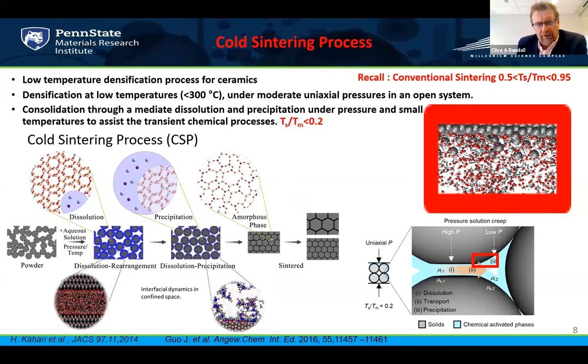So we've taken a very different direction. It's still very much in its infancy, and it was inspired by geological reading. It's really a low temperature densification process, densifying at low temperatures below 300 degrees with moderate uniaxial pressures. The key point is adding a chemical additive that will enable dissolution and reprecipitation and also be transient, so it can either evaporate or transform